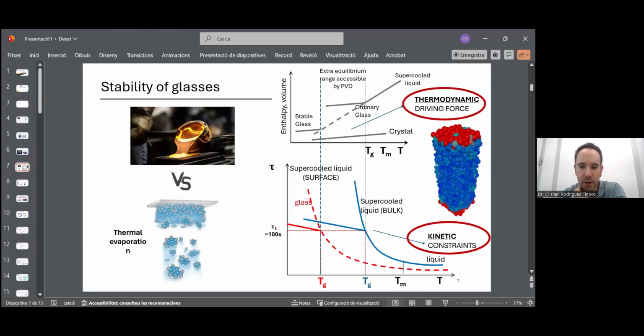So here, the blue line is the same relaxation time I was showing before, the bulk relaxation time of the supercooled liquid. At the glass transition temperature, the system goes out of equilibrium, typically considered to be 100 seconds. This red graph here is just a schematic. It's not a real measurement, but it is a representation of what would be the relaxation time of the surface layer of the glass as it grows by physical vapor deposition.